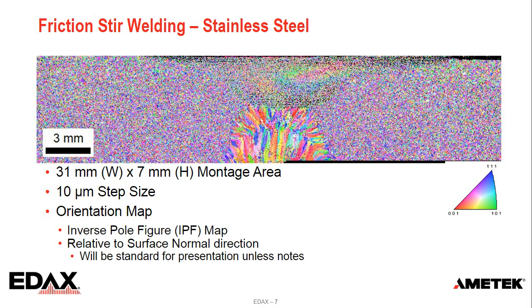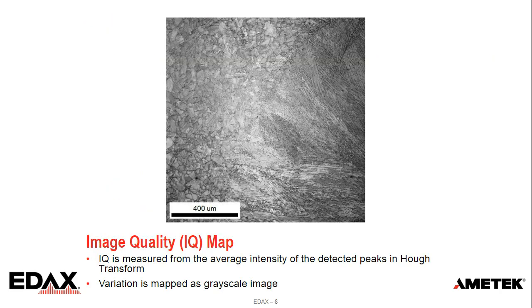And we have the little colored stereographic triangle that shows how the colors correspond to orientation. So if it's red, it's a 001 cube face orientation for the cubic faces in steel. If it's blue, it's a 111. And so we see the weld nugget there in the bottom center. You see a little bit on the top where it's transitioned, and you see the base metal to both sides. If we zoom up along the interface in there, this shows what we call our image quality map. Image quality is a measure we get from measuring the average intensity of the detected diffraction peaks in the Hough transform. We measure that value, and then we map the variation as a grayscale image, and we see different contrasts.